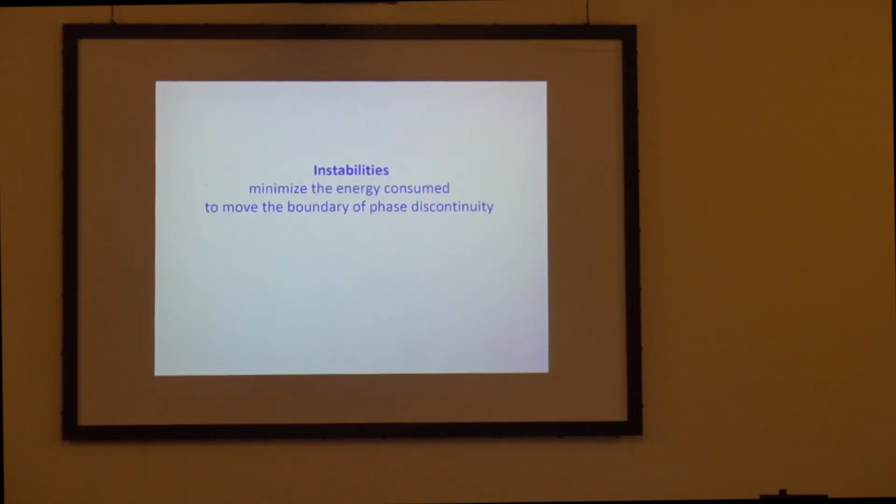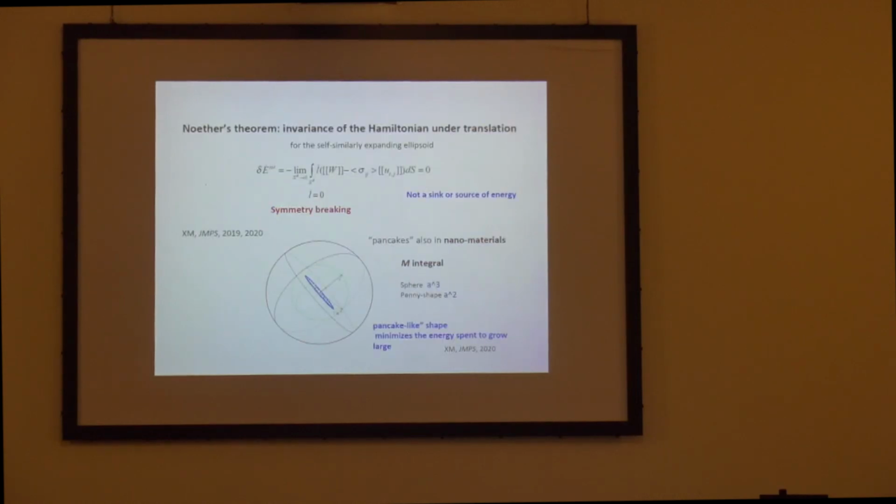So, how do we get the instabilities? The shape of the boundary we may call an equilibrium shape, so that the boundary does not become a source of energy. From the dynamic J integral, you will get this expression, L dot the boundary velocity, and the jumps, the double brackets denote jumps. This is a well-known formula in phase transformation. So to have this zero, there are two possibilities. Either the quantity in the parentheses is zero, which is preserving the symmetry, or L dot is zero.